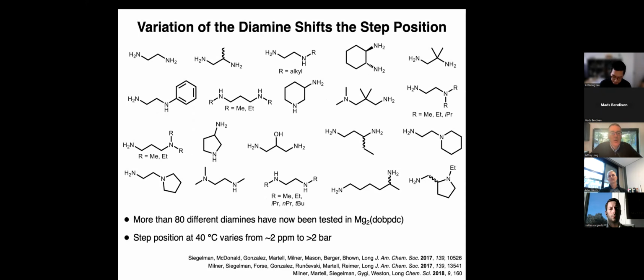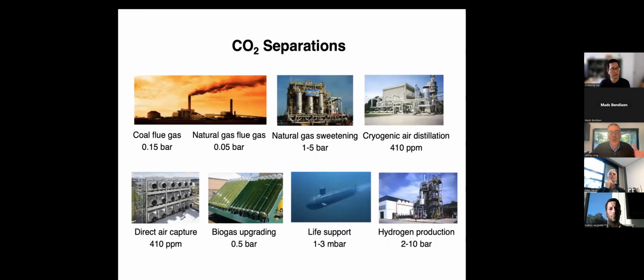And so we've studied now many different diamines, more than 80 different diamines in this material. And at 40 degrees C, we can adjust the step anywhere from 2 parts per million, where you're capturing very deeply from air, to past 2 bar, which might be useful for a high pressure gas mixture doing the CO2 separation. So of course, there are many, many places we'd like to efficiently remove CO2 from a mixture, and we need to be doing a lot more of this. But by changing the diamine, we can try to optimize for a separation process targeting these various CO2 containing mixtures.